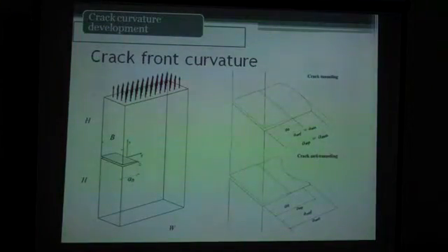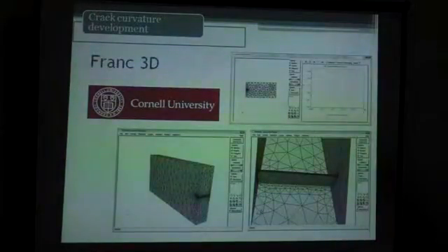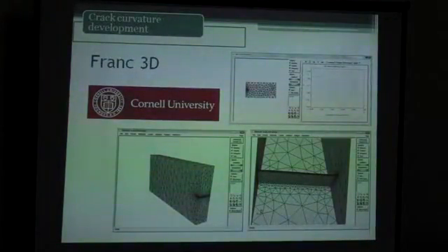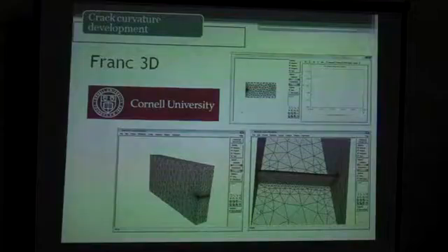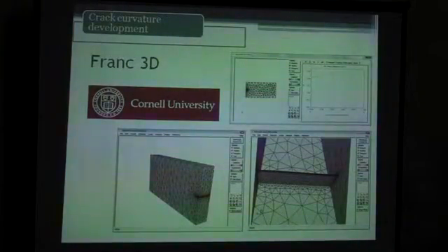And we're going to calculate that by using the stress intensity factor solution, adopting a crack propagation equation, for instance Paris' law, or a more improved equation, and then we're going to slightly increase the crack size along its front proportionally to the ΔK, and then we're going to remesh and recalculate again, and calculate all the transient effects that happen in there. And we did that with Franc3D together with Abaqus. So we did all this very refined modeling, and we did the step-by-step growth of this crack.